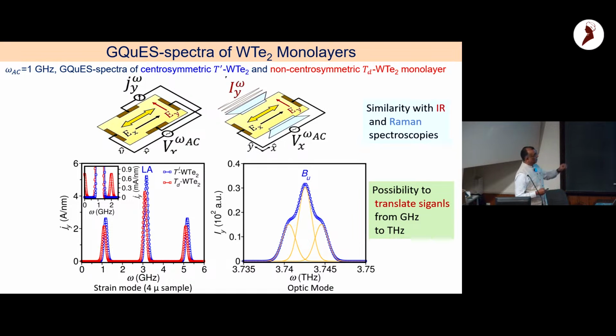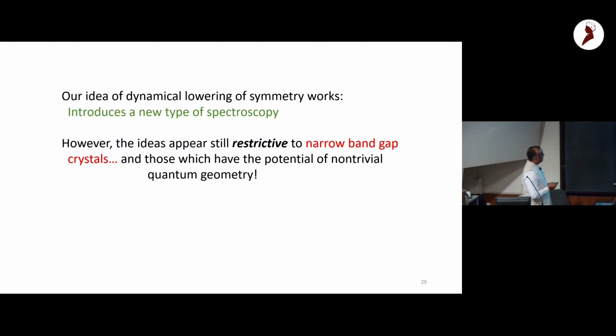Okay, so these are specific predictions which we hope experiments should be able to validate. Of course, the exact location of peaks will not match experiment exactly, but we expect them to be within 5 to 10%. So our idea of dynamical lowering of symmetry works, and based on that, we introduced a new type of spectroscopy. However, these ideas are also still restrictive because you need to have a narrow bandgap semiconductor for this. And that we haven't solved yet.